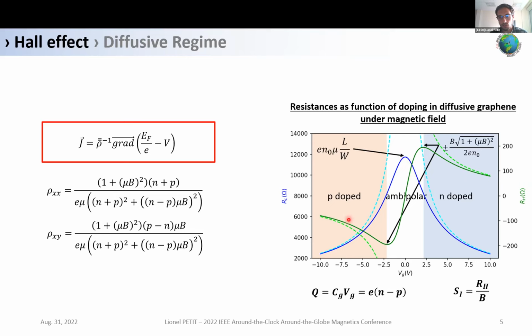If now I switch to the green curve, which is the Hall resistance, we can see that when graphene is highly doped, we retrieve the 1/n behavior, which is typical of the sensitivity, because the Hall resistance is just proportional to the sensitivity. But in between, it's more complicated, and it is due to the ambipolar behavior of graphene. And to increase the Hall resistance, we need to decrease this n0, which is the residual charge density due to both temperature and impurities. So we need very clean graphene.